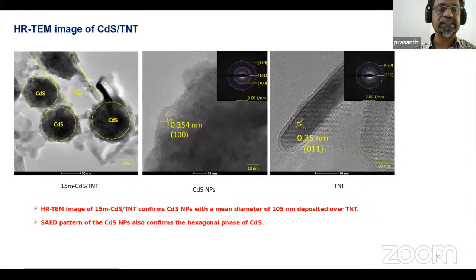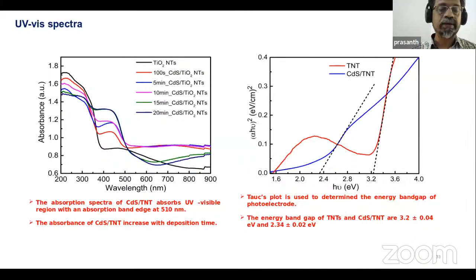In this CdS, the TEM images show that the CdS is nicely decorating the nanotube structures. And when we are decorating the TiO2 nanotubes with CdS nanoparticles, then you can harvest more light into the system, compared to normal TiO2 alone. That's showing the black curve. And when you are increasing the deposition time, that will increase the size of the CdS nanoparticles. And at a certain point, when the stoichiometry is proper, that shows a better current, light absorption in the structure. After that, it will again decrease.